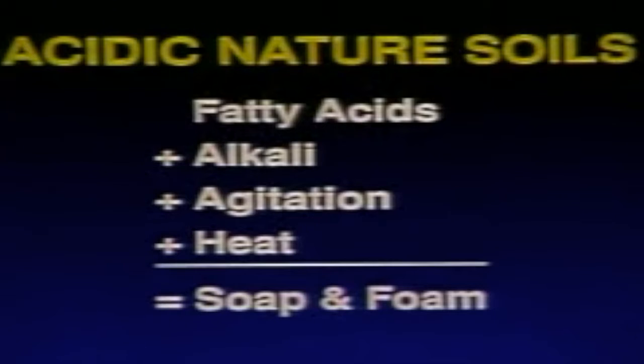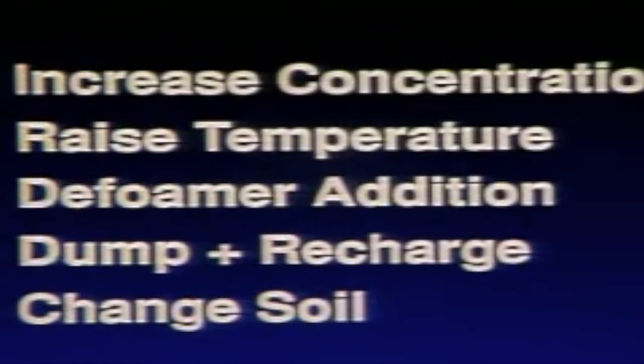Soils with an acidic nature, such as some of the soluble oils and soils containing fatty acids, can create severe foaming problems. The reason being that under heat and in an alkaline system, these fatty acids convert to soap, which overloads the defoaming system when the soil reaches a saturation that exceeds the anti-foam capabilities of the cleaner in solution. Fatty acids plus alkali plus agitation and heat equals soap and foam. When the incoming soil load exceeds the particular cleaner's ability to control it, this saturation point generally reduces the tank life drastically. If you should encounter these types of soils, you have three alternatives.